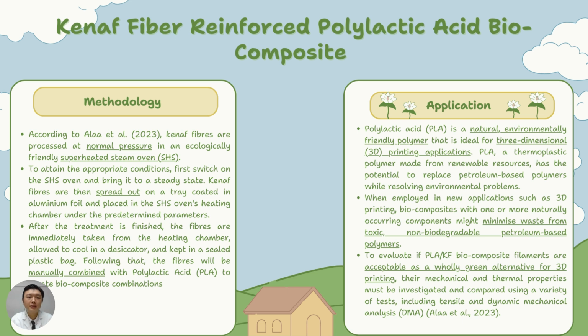So this is the fourth one, where we talk about the kenaf fiber reinforced polylactic acid biocomposite. In this methodology, we will use the superheated steam oven (SHS). First, the SHS oven is switched on, and then the kenaf fiber is spread out on a tray coated with aluminum foil and placed in the SHS oven for heating. After the treatment is finished, the fibers are immediately taken from the heating chamber, allowed to cool in the desiccator, and sealed in a plastic bag. Then the fiber will be manually combined with the polylactic acid (PLA) to create a biocomposite.